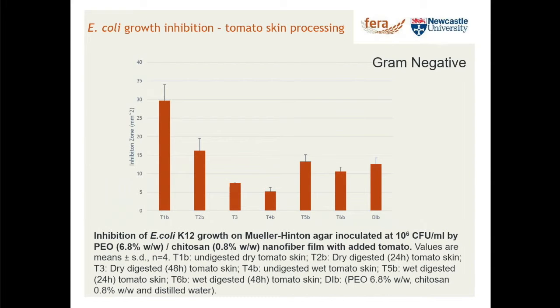One of the things we can do is measure the size of those zones of inhibition. So the bigger the zone of inhibition, the more antimicrobial the effect. This is just to demonstrate we see a range of antimicrobial activities. And this is actually a comparison of different processing regimes on that tomato skin we'd incorporated. So on the right-hand side, this is the typical zone of inhibition in square millimeters seen for, in this case, a chitosan PEO mix with nothing added to it. So as expected, chitosan in the fiber form has an inhibitory effect. But when we start adding tomato skins into it and processed tomato skin, we see a much bigger inhibitory effect.